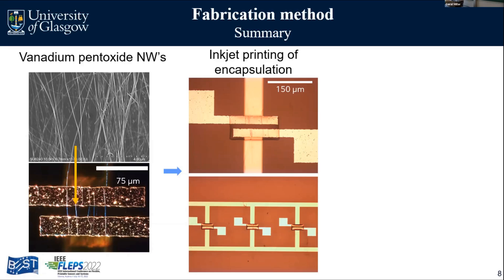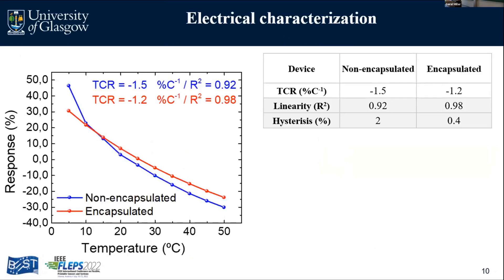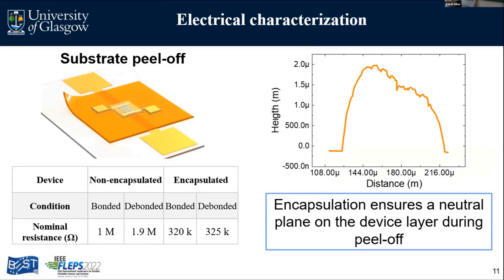A follow-up question asked about the thickness and surface roughness of the encapsulant. The presenter confirmed the layer is around 2 microns for a single printed layer. By adjusting the speed of the electrohydrodynamic printing, the thickness can be tuned — higher speed gives a thinner layer, though too high a speed may create gaps in coverage. Multiple layers can be printed on top of one another to increase the thickness as needed.